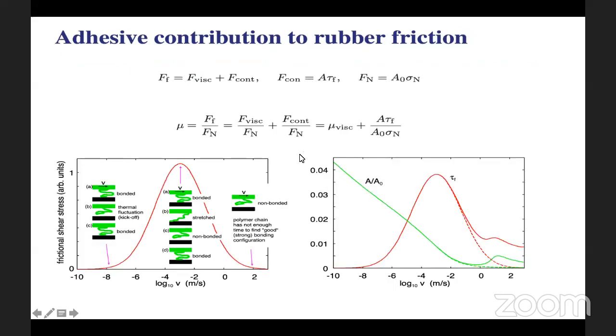Now the adhesive contribution, as I have already said, happens at low velocities. You have polymer chains; this is a schematic and idealistic diagram. You have chains on the elastomer surface which come in contact with the rough surface, and then they stick to the rough surface. When you start to move, these chains are stretched. They are stressed long enough, and then they will break the contact and release energy. That energy is the fundamental reason for how friction appears due to adhesion.